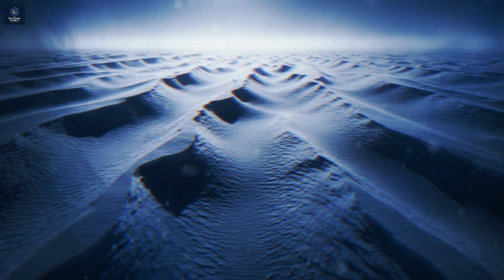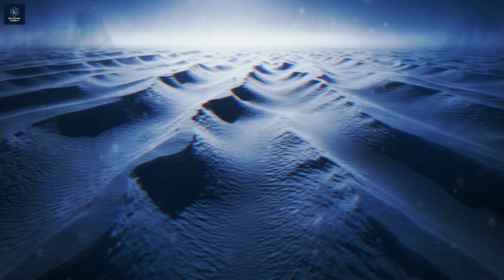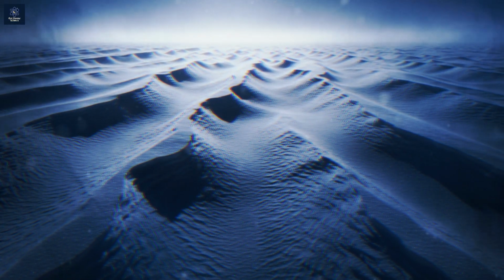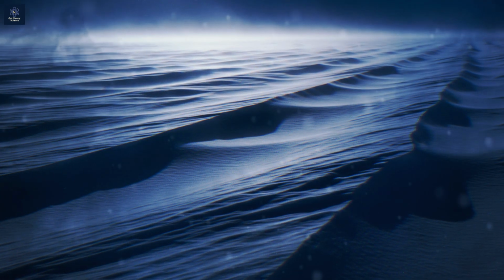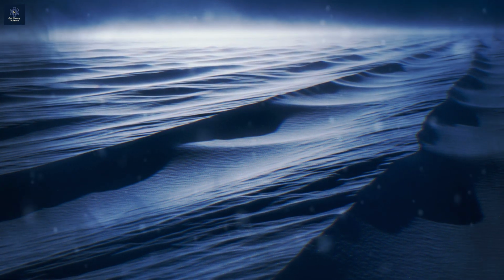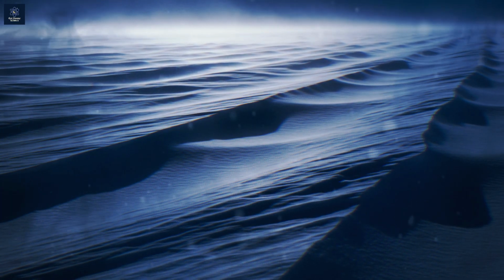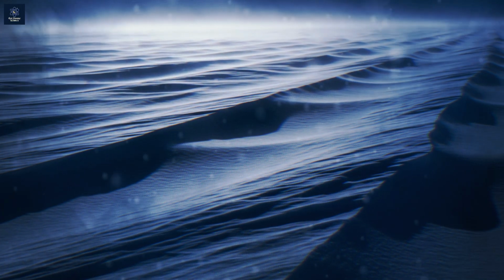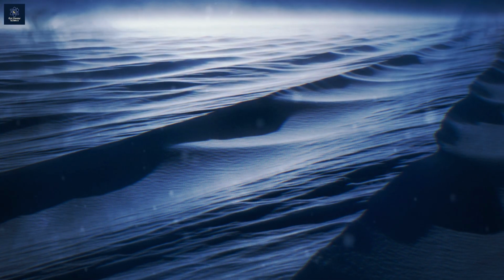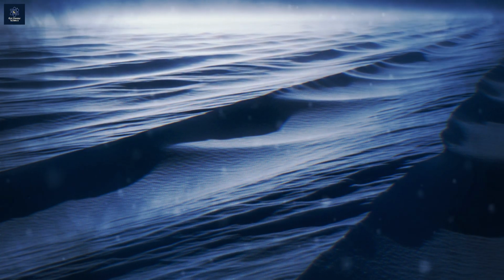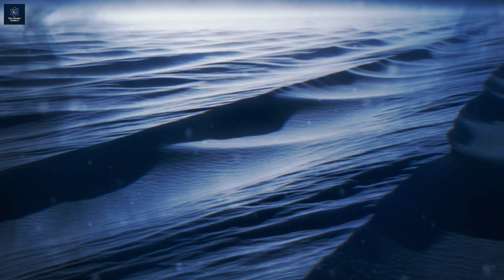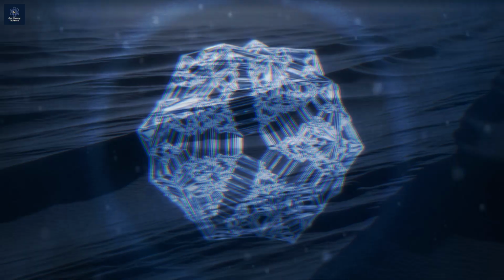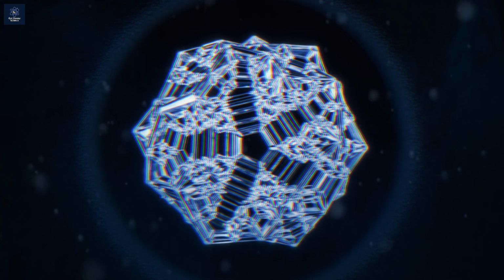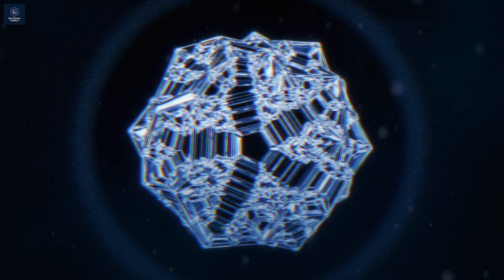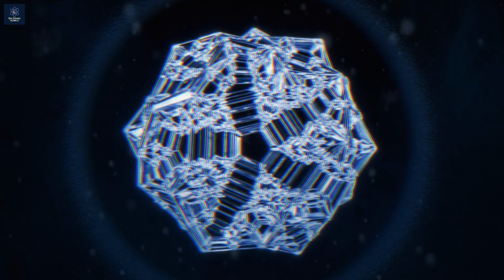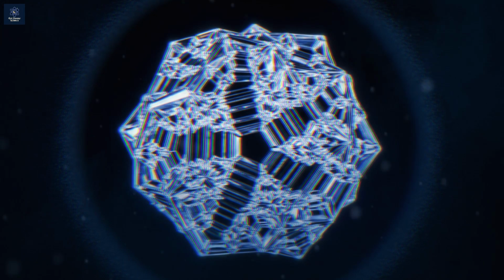Research by physicist Kenneth Libbrecht has documented this relationship extensively. He found that the most ornate stellar dendrites form when humidity is high and temperature is around -15 degrees Celsius, about 5 degrees Fahrenheit. Lower humidity at the same temperature produces simpler plate crystals. This happens because abundant water vapor provides more material for crystal growth, and it also affects how quickly molecules can move across the crystal surface to find their attachment points. Humidity is like the paint supply for nature's snowflake artist.